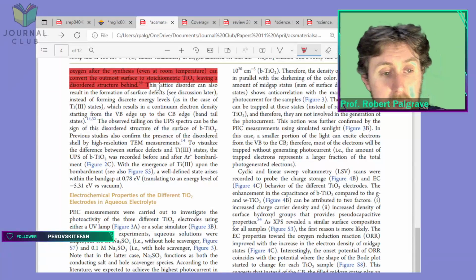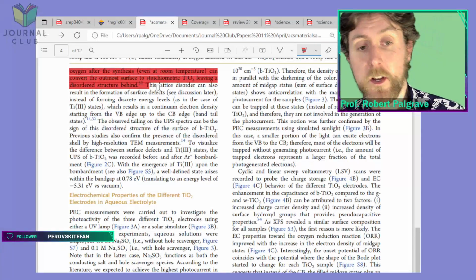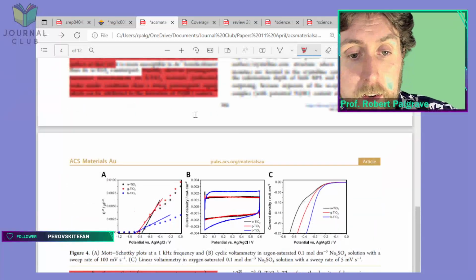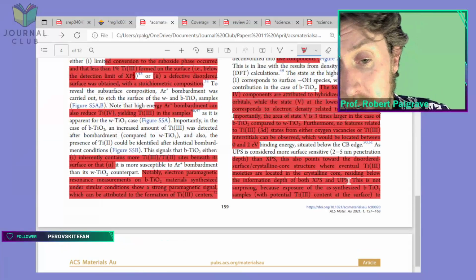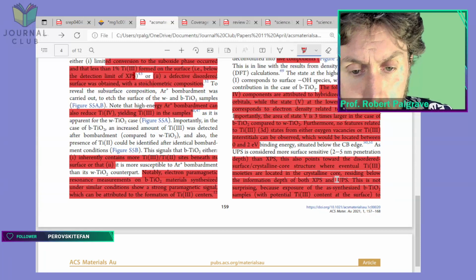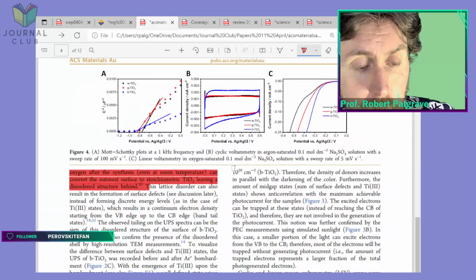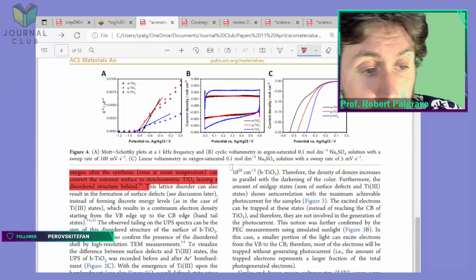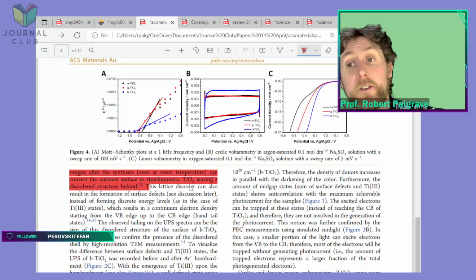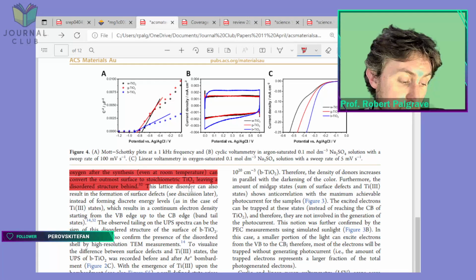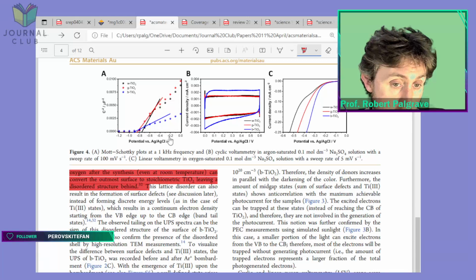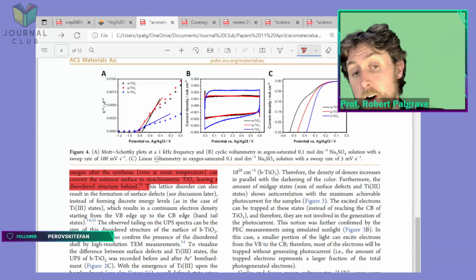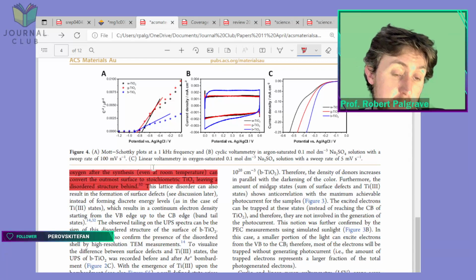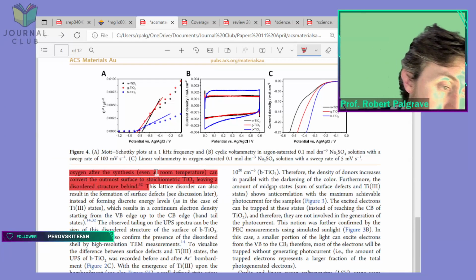detect through electron paramagnetic resonance, or detect with, or sorry, not detect with the UPS. Sorry, the UPS doesn't detect it. So that's their kind of hypothesis, and they say that the reason that happens is because once you take the samples out of the furnace, into air, then the surface becomes oxidized just by reaction with oxygen. The surface Ti3+ becomes oxidized.